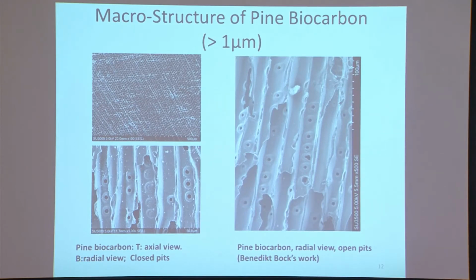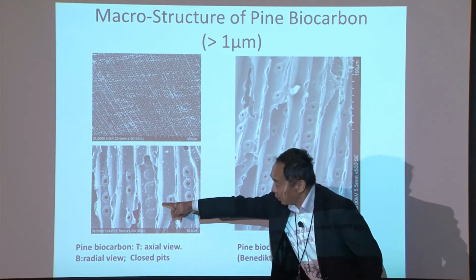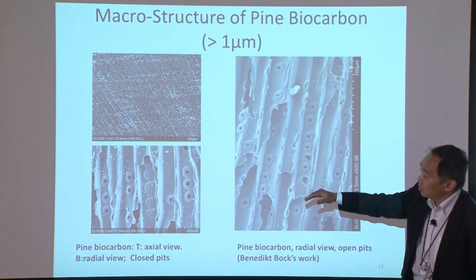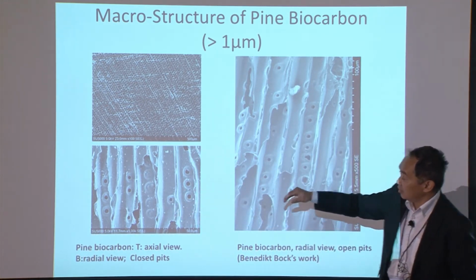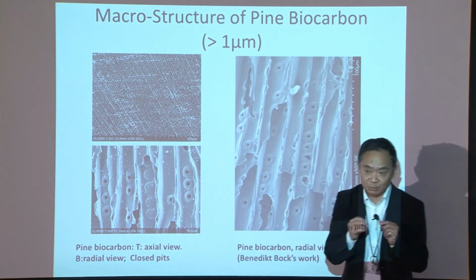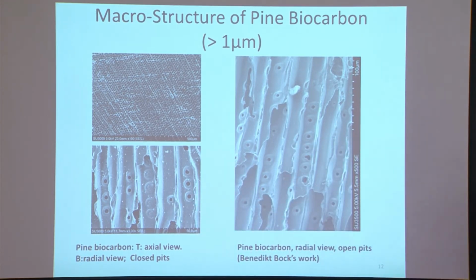This is softwood, a pine. If you pay attention to the small scale features here, this is called a pit. We can control the process conditions to close and open this pit so as to improve mass transport of, say, ions in the electrolyte in electro applications. The bottom line is that if we treat these wood materials carefully, we can retain or control the structure in wood.